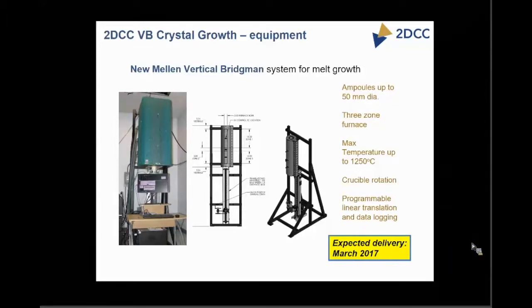It's a typical conventional 3-zone furnace, and the maximum temperature of this system is limited to 1250 C. Most of the materials we're interested in, most of the growth processes are going to be done in quartz ampules, and so 1250 C is reaching the limit of the quartz. There are some materials of interest that go to higher temperatures where you have to use other materials such as platinum, iridium, etc. But this particular system, which is going to be one of the key pieces of equipment in the bulk growth, will be set up to focus on growth up to 1250.